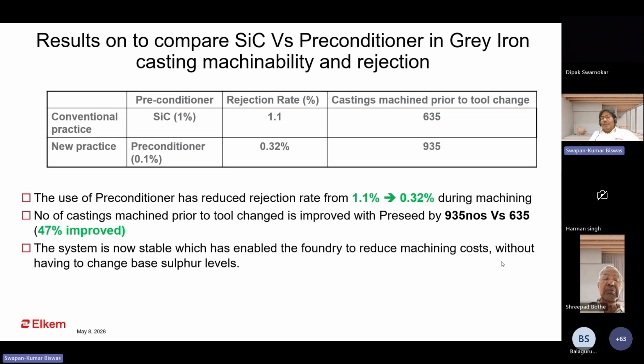When they went for the preconditioner at 0.1%, you can see the rejection came down to 0.32%, and the number of castings they were able to machine with a single tool is 935. So there is around a 47% improvement in machinability. Now you can calculate which is more beneficial cost-wise: going with silicon carbide at 1% with 1.1% rejection, or with the preconditioner. When we demonstrated to the foundries, they switched over from their earlier package to this new package.